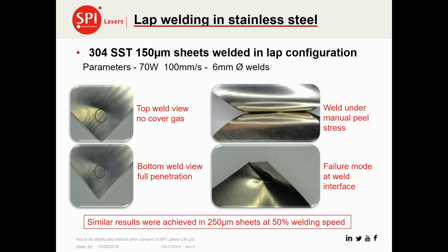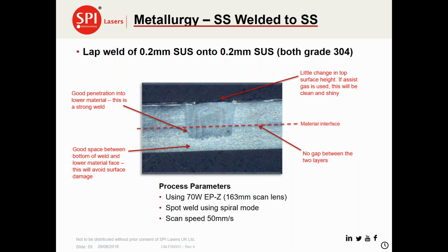Looking at, again, the metallurgy of this particular weld, this is the stainless steel to stainless steel weld. We can see a number of things here. The observations are that we actually have good penetration into the lower material from the upper material. We really can control the depth of the weld itself. You can see almost where we've been able to control each individual part of that weld as we have used the spiral geometry through the top into the bottom layer.